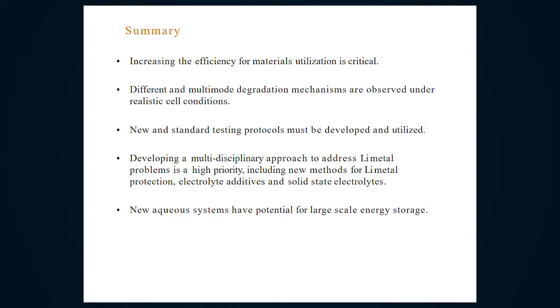And for the systems we are talking about, with high material utilization and thick electrodes, we believe different degradation mechanisms show up. It's different from what we see under dilute conditions, and we really need to understand that. If we really want to work with the whole community, we encourage the whole community to work with us, look at the realistic testing conditions we are using, and try to compare the results on level ground.